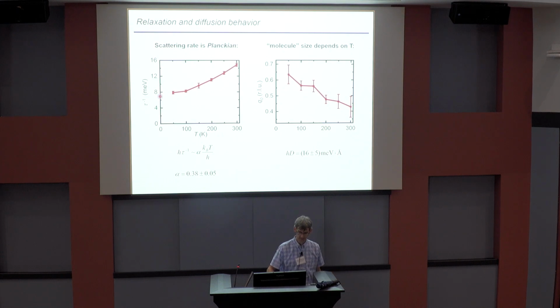But if you go to larger momentum, there's something that you can put a line through if you wanted to imagine this thing was linear in temperature. And if you fit that line, alpha is about 0.38. So it is Planckian, at least as Planckian as any resistivity is. And I'd just like to point out that all these numbers are real numbers, okay?